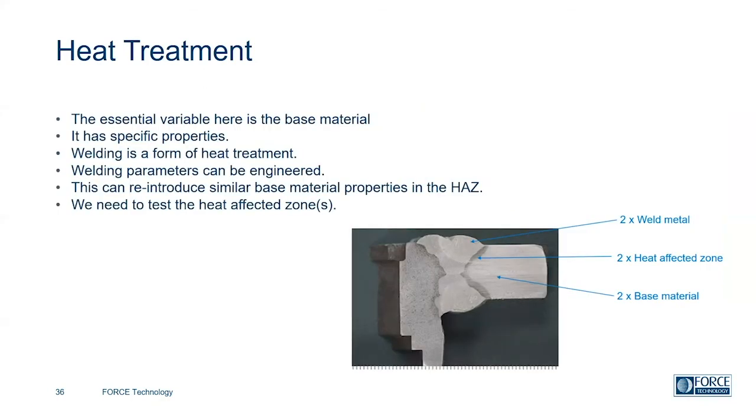But the clever thing about welding is that the welding parameters can be engineered, and this can reintroduce similar base material properties in the heat affected zone. And the heat affected zone is, after all, the base material. So if we can show that the weld or the repair has similar properties as the base material, then we may not have to do the post-weld heat treatment.